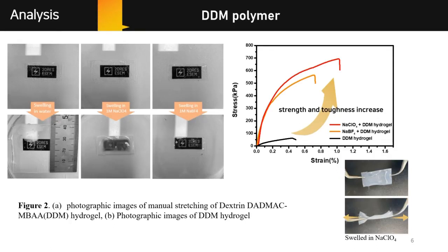Black line data is DDM hydrogel before swelling. Red line data is DDM hydrogel swelled in NaClO4 solution, and orange line is swelled in NaBF4 solution. As shown in the stress-strain curves, after swelling in ClO4 or BF4 solution, the gel's strength and toughness are increased.